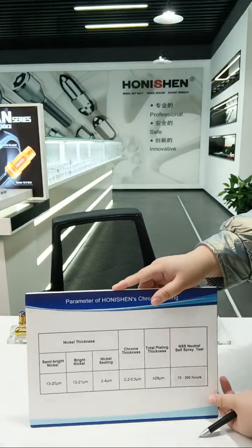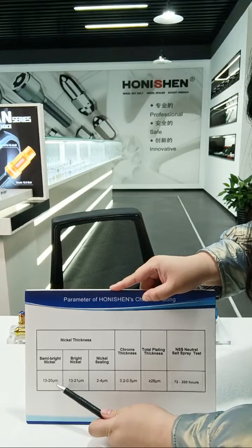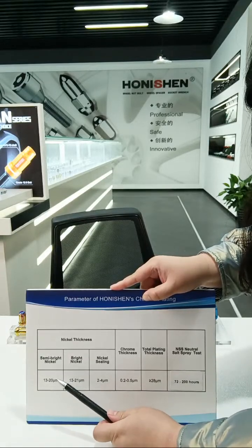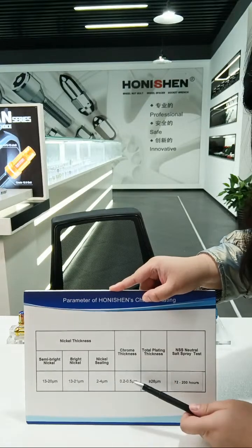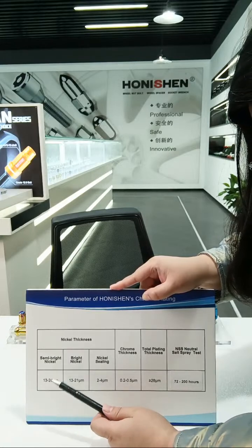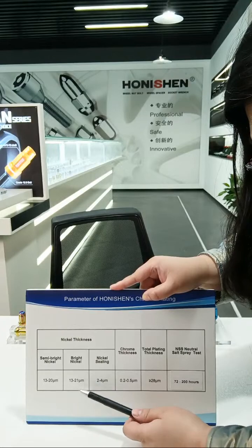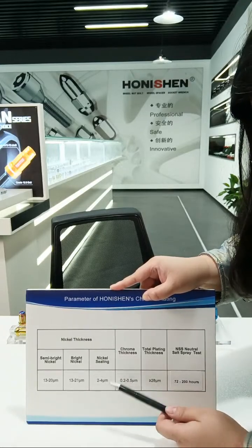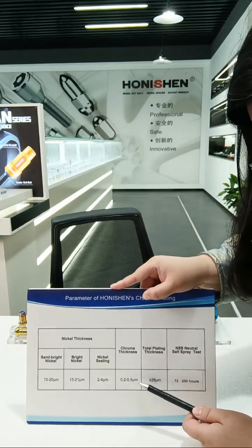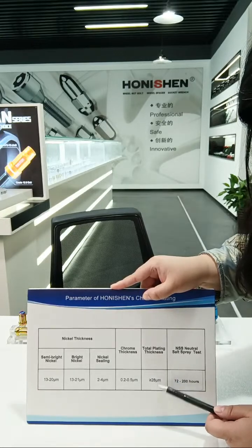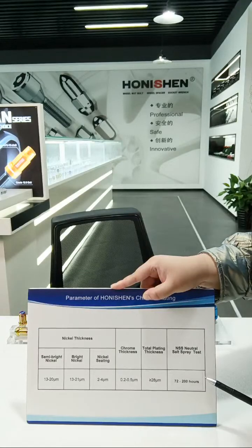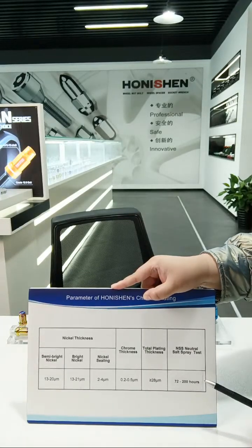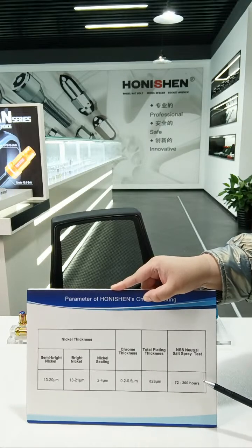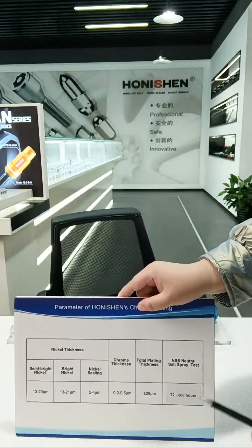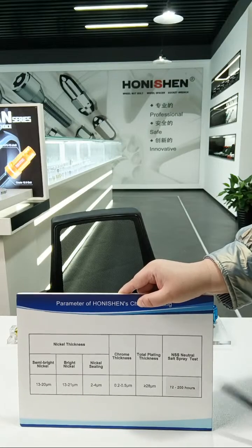See this form. Our chrome coating consists of 3 layers of nickel and 1 layer of chrome. The semi-bright nickel thickness is 13 to 20 microns, the bright nickel is 13 to 21 microns, the nickel sealing is 2 to 4 microns, and the chrome thickness is 0.2 to 0.5 microns. So the total thickness is greater than or equal to 28 microns. We promise all the products pass 72 to 200 hours neutral salt spray testing. Then the color fastness is very good, and the anti-rust performance is very good.